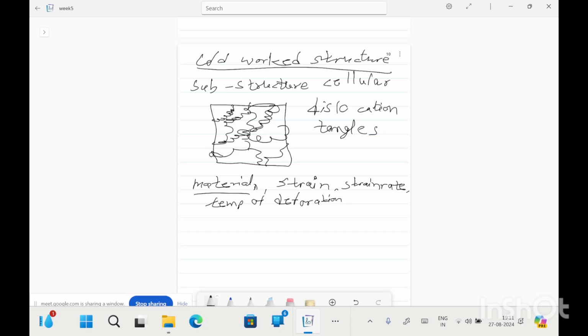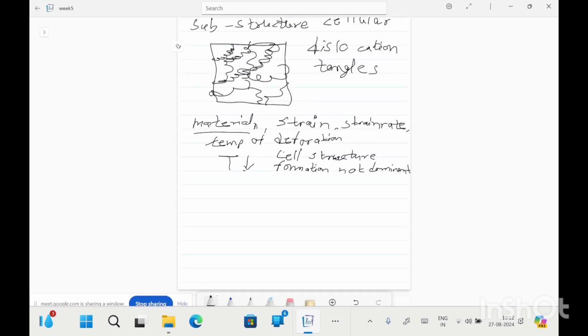At a low temperature, the development of cell structure is less dominant. If the temperature is low, then the cell structure will form very slowly or after a very long time. At high temperature, dislocations have the activation energy to cross the barrier that further participates in the deformation process and increases the dislocation density further.